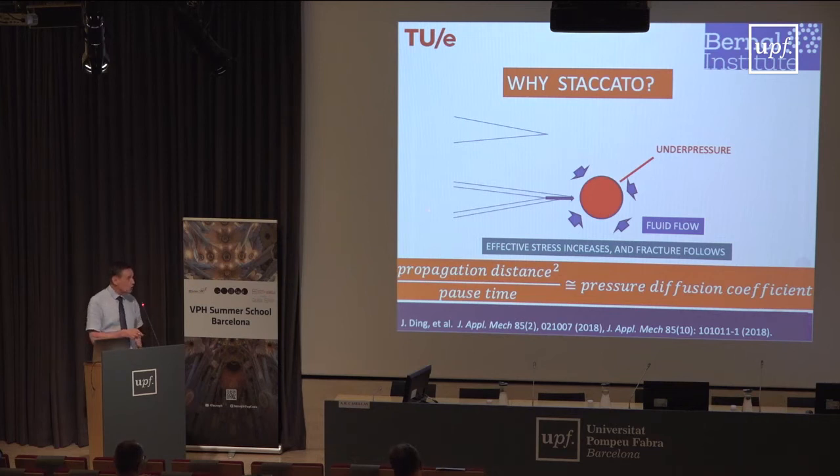Now, what you can show in gels is that typically the propagation distance squared divided by the pause time is in the order of magnitude of the pressure diffusion coefficient. What is the pressure diffusion coefficient?